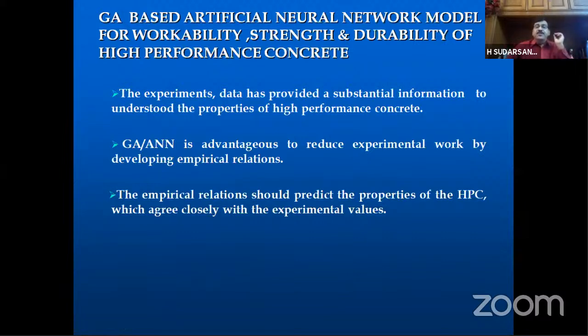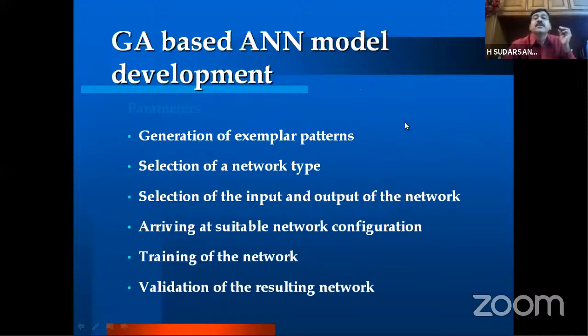So the GA-based artificial neural network model was prepared for workability, strength, and durability. For predicting the strength, that is compressive strength, tensile strength, and flexural strength. And for the durability, for predicting the resistance to acid attack as well as the permeability. For permeability, we have taken chloride ion permeability. So with all this experimental data, we have trained the genetic algorithm based neural network model.